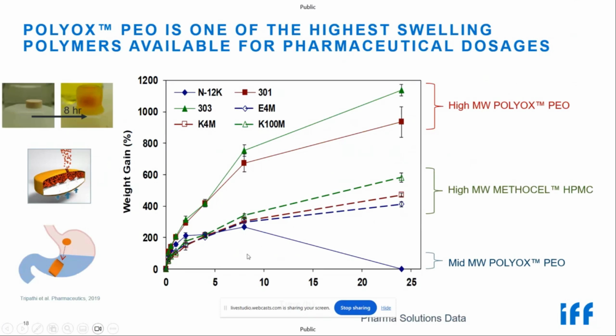The mid molecular weight PEO down here in the blue is a 1 million molecular weight polymer. We can see the initial rapid hydration similar to the high molecular weight polymers, but then this plateau and then decrease in the weight gain up to the 24-hour mark. This is happening because it's eroding into the water, and it's fully eroded at the 24-hour mark.